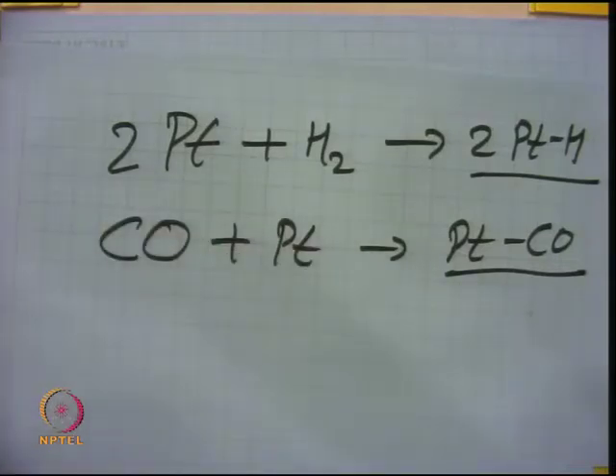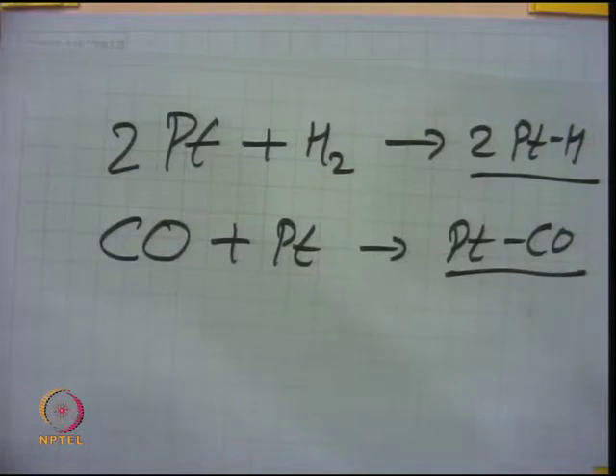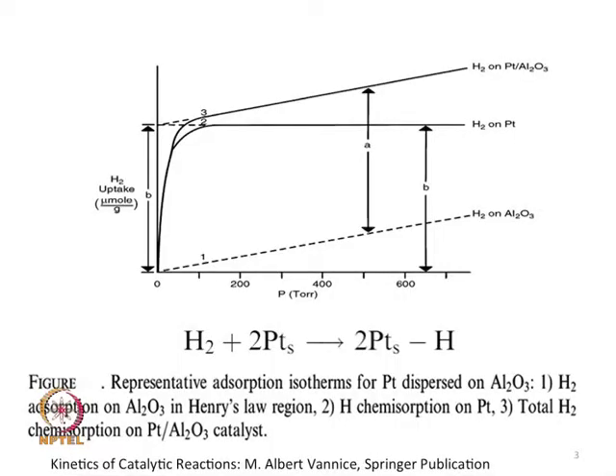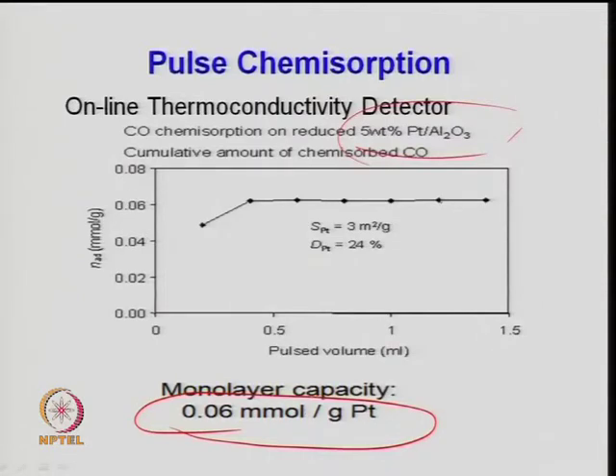CO adsorption can be associative or dissociative; most of the time for platinum it is associative — Pt + CO giving a PtCO chemisorption. By knowing this stoichiometry you can determine the dispersion or percentage dispersion. You can also determine the crystal size because it is related to the monolayer depth and atomic size. Most metals are supported on alumina, silica, or similar materials. When discussing a bimetallic catalyst, the support may also have chemisorption properties for the reactive gas.